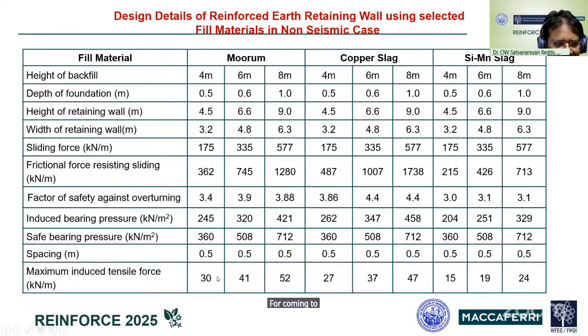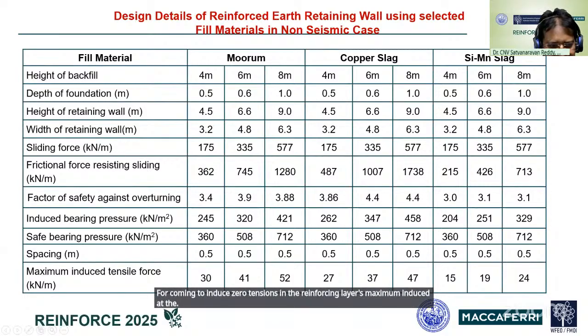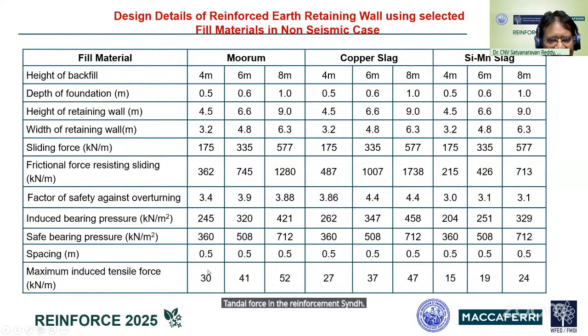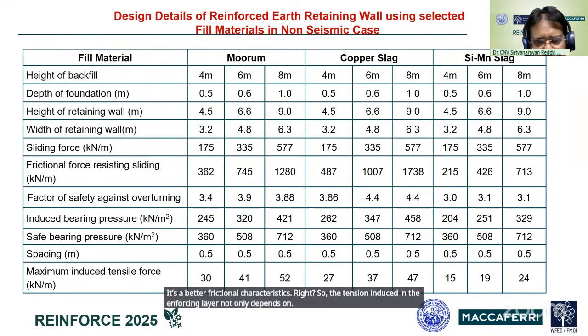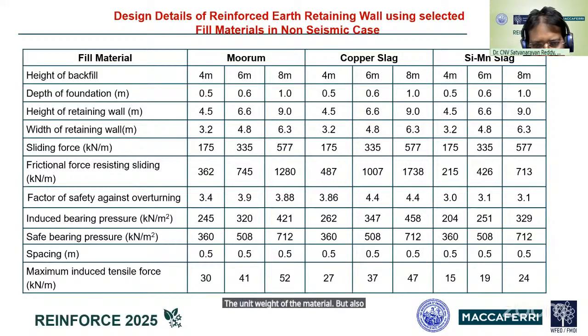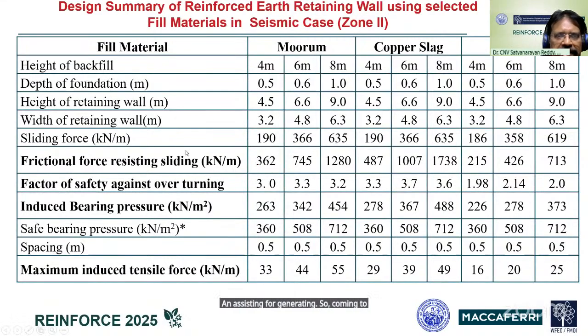So coming to induced tensions in the reinforcing layers, the maximum induced tensile force in reinforcements: you can see for a given height, silico-manganese slag has resulted in the least tensile force, and even copper slag, though it is a heavier material, has resulted in lesser tensile force. This is due to its better frictional characteristics. The tension induced in a reinforcing layer depends not only on the unit weight of the material, but also on its friction. The higher the angle of interfacial friction, the lesser the tension induced in the reinforcing layer, and the higher the pullout resisting force generated. So coming to the seismic design pertaining to zone 2.